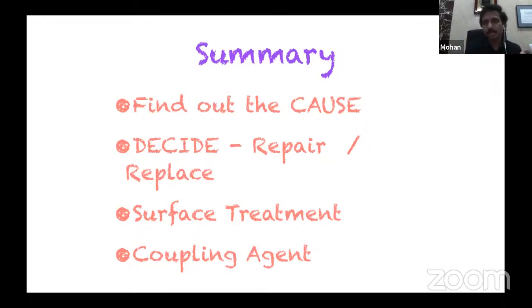Surface treatment, I already told you: diamond burr abrasion, then air abrasion, then acid etching. All these possibilities are right in front of us. After that, the coupling agent is very simple. I've not complicated it. And then you put the bonding agent, and then you apply the composite resin and proceed further with the finishing and polishing.